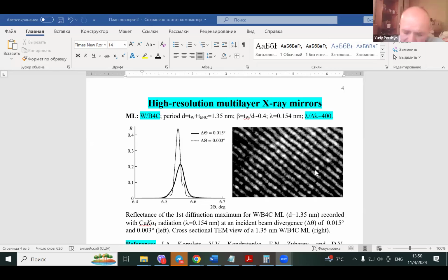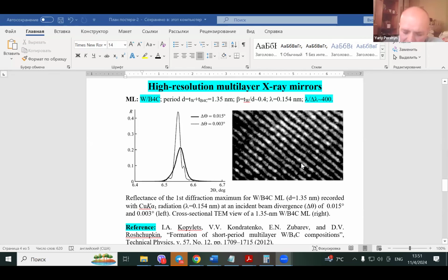Usually crystals are used as monochromators for X-rays, but they have limited application due to small d-spacing. So they cannot be used for the wavelength range longer than 2 nanometers, or energy shorter than half of keV. Organic crystals are used for this wavelength spectrum, but they have low reflectivity and low stability. Multilayer combine the advantages of both types of monochromators.